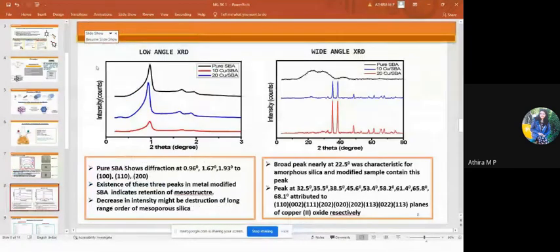The next one is the XRD pattern, low angle and wide angle. In the low angle XRD pattern, pure SBA shows diffraction peaks at 0.96 degree, 1.67 degree, and 1.93 degree, corresponding to the reflection planes 100, 110, and 200. These are the characteristic peaks of mesoporous SBA-15, and retention of these peaks in the modified sample indicates that the parent structure is unaffected.